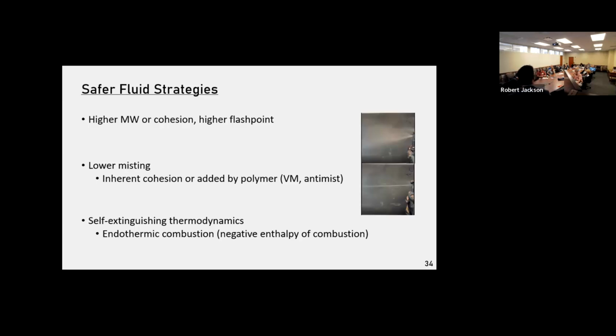I tend to say base fluid because we've maybe gone from petroleum to synthetic esters, to PAGs. You can also lower the misting by adding things like polymers, viscosity modifiers, anti-misting agents. Here's some real basic spray testing we did with 0.01% of the polymer. It changes completely the spray pattern from a spray, high surface area, high combustibility, to a jet. And then the last piece is self-extinguishing thermodynamics, so phosphate esters.